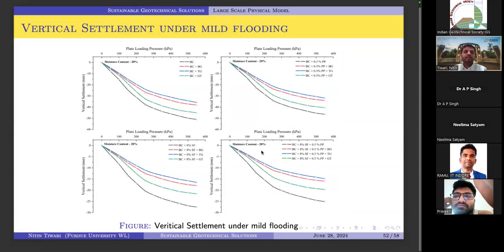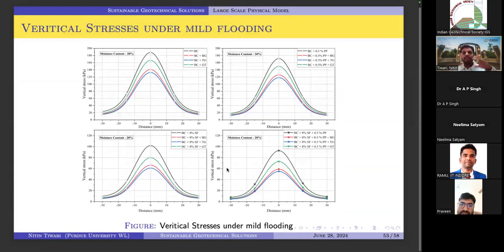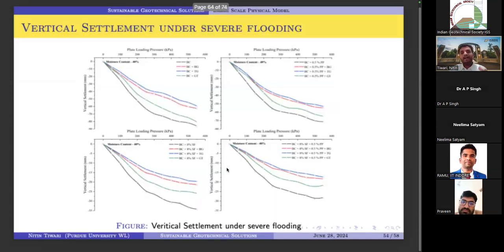I'll not go really in depth, but you can see that even with the treatment, going up to 500 kPa pressure, the vertical settlements are reducing in every condition. Even for an initial 50 mm of displacement, it goes back with the silica fume and polypropylene fiber to almost 10-15 mm. So a huge reduction. The same goes for the stress bulb, which is reducing, so the stress distribution is also less. Even in the severe flood condition, the untreated samples go to almost 90 mm of displacement, but with the treatment you can achieve almost 10-15 mm, the same as the mild condition. So ultimately your treatment is working well.